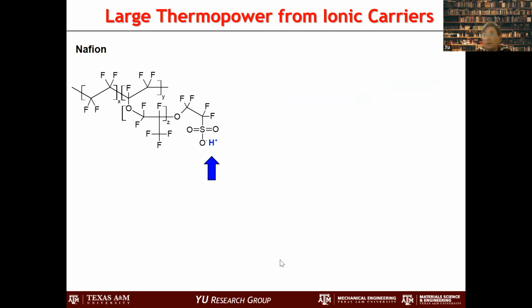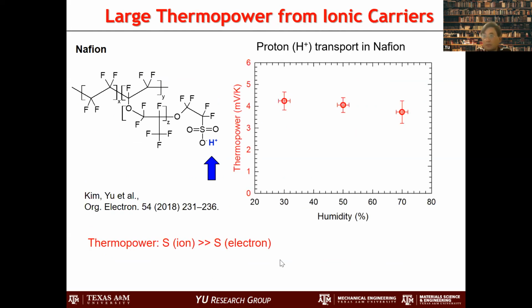For example, Nafion is a polymeric material that we used before, and so we actually measured, and it happened to be pretty large here, right? So this thermopower is about 4-5 millivolt per Kelvin, as opposed to the conventional one, which is about 0.1. So you have quite large thermopower. So there is actually quite a promising characteristic here.